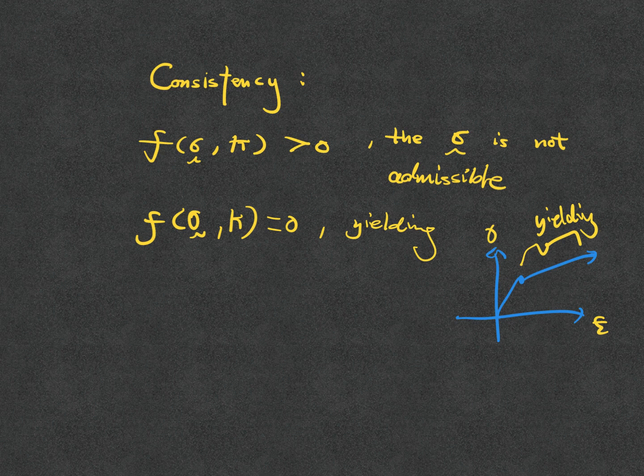In this whole region, from here to here, F, which is a function of sigma and kappa, is continuously equal to 0. Does that make sense? Okay, because larger than 0 is impossible. Smaller than 0 means it's elastic. But I'm continuing loading the material, so it doesn't make sense that it suddenly becomes elastic, right? Okay, unless you don't have convexity. Okay, you see what I mean?